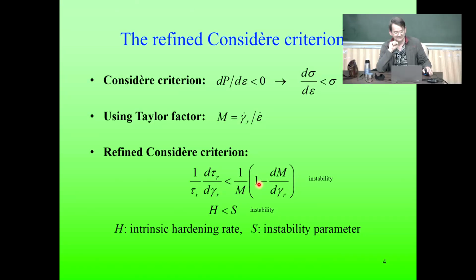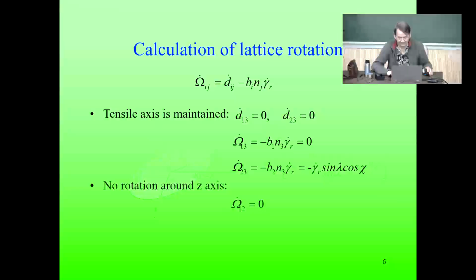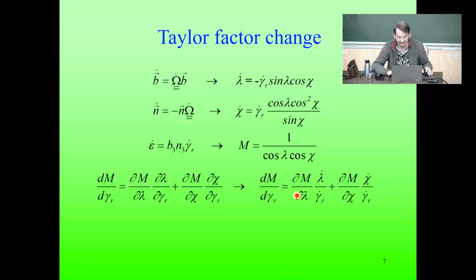And we will see what the simulation calculation shows, what is happening because of orientation change in single slip and tensile testing, whether it is going to help the stability of the crystal or not. That's one of the results we are going to get now. Okay, so the simulation gives a formula for dm d gamma r. Actually, this is the formula. What we get is a very nice analytical formula, and the whole calculation can be done by hand. There is no need for a computer.